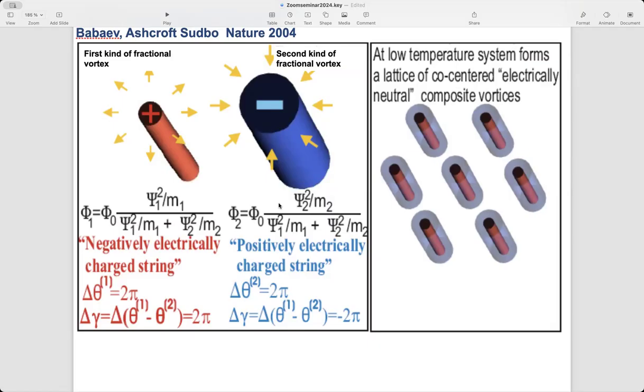We looked at the consequence for the phase transition in the system. Again, starting under the assumption that we have some kind of system, be it metallic hydrogen, be it a condensate somewhere in a neutron star, then if one exposes it to a magnetic field, as one example, the only finite energy vortices it could form in an external field will be the vortices which have composite nature, that will have winding in both condensates.